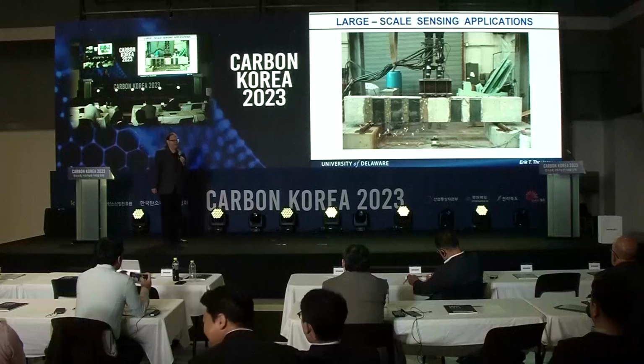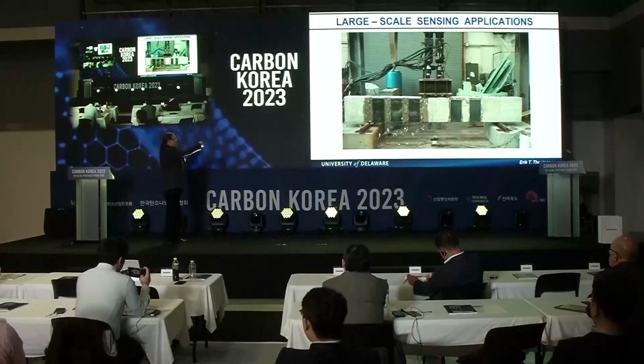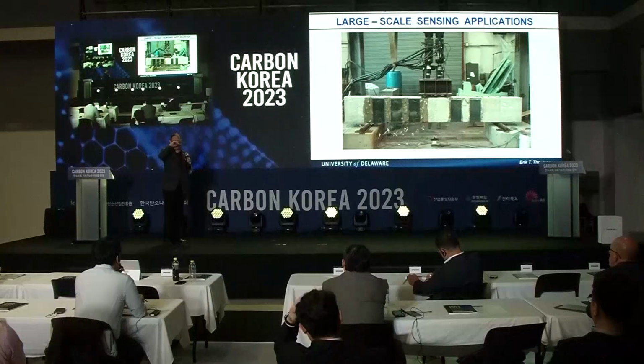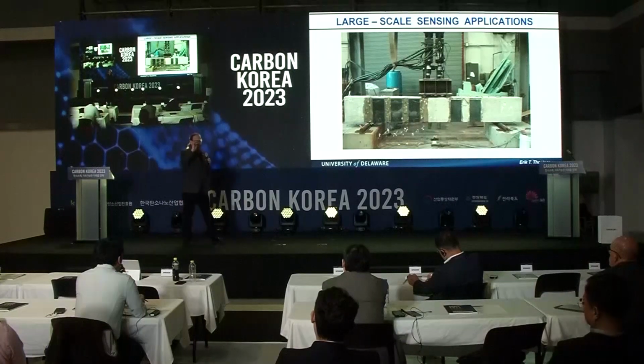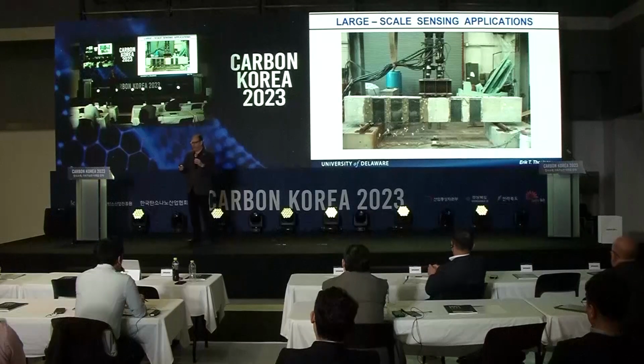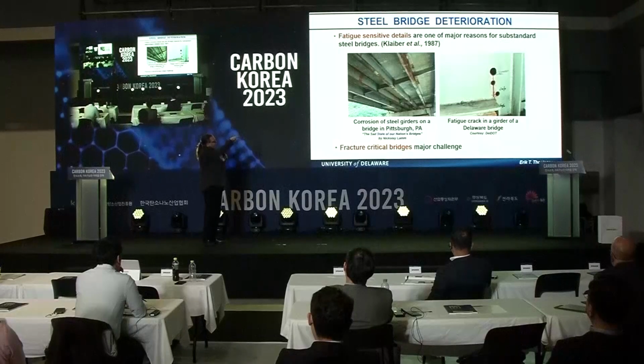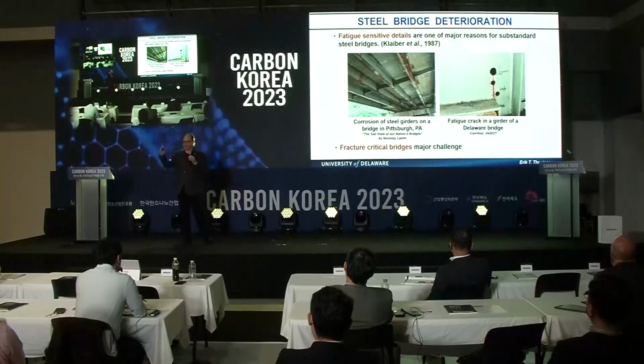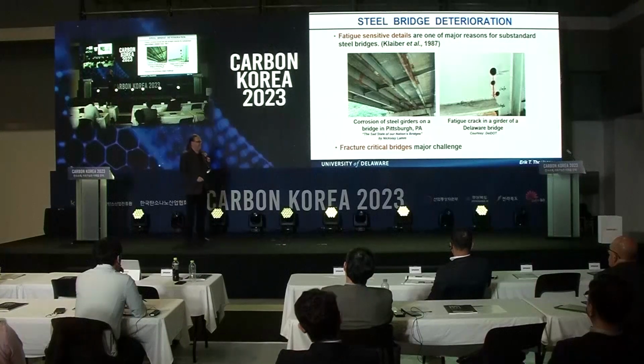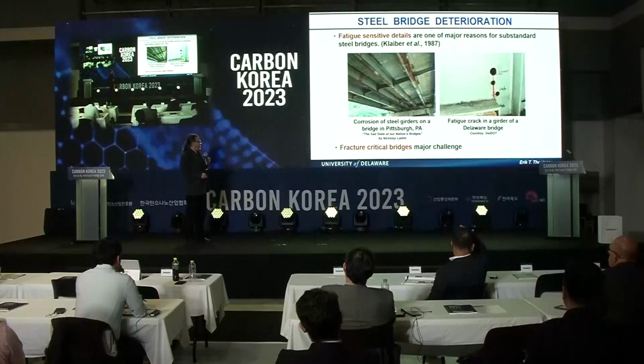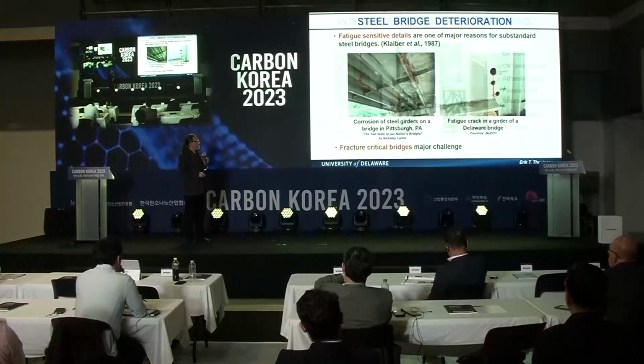So again, because we can scale this process, this is a concrete beam. I won't talk too much about this, but that beam is 4 meters long, and it has shear U-wraps on it and also integrated sensors. And one of the biggest issues is fatigue damage in civil infrastructure. On the right-hand side, that's actually a bridge in Delaware that we went out and did some monitoring on. And what you can see, there's holes drilled, and that's the traditional way of trying to repair a crack: you drill a crack stop hole to blunt the stress concentration at the tip.